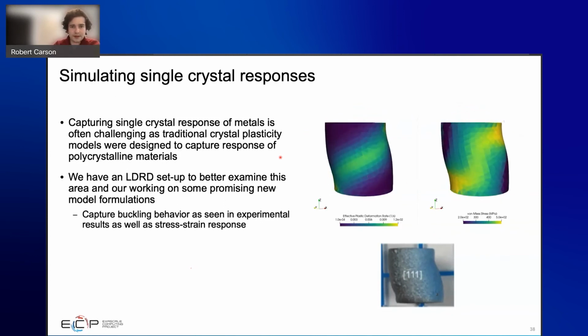But I just want to show we can model the deformation of single crystals, and we do this doing compression type things. We see some nice buckling form in our materials, and when we actually looked at the experimental data for these single crystals, we see that buckling as well. So it's really cool seeing our simulations actually capturing some of these experimental responses.